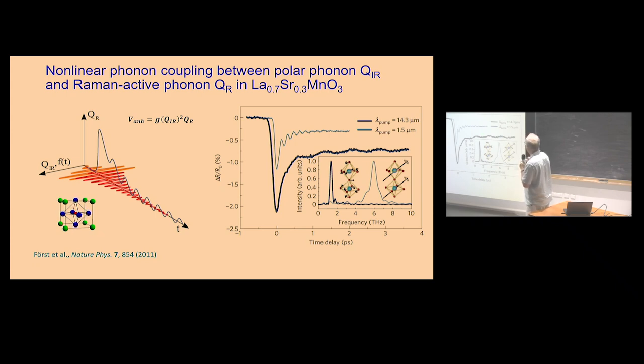They found that even if they pump at 17 terahertz, they obtained a peak around 1.5 terahertz. And when they pump at higher frequency, they obtained a peak at 6 terahertz. So there was activation of phonons due to nonlinear coupling. The infrared active phonons, due to quadratic coupling, and this is, I think, a very important formula, just remember it, take it home. I will use it in many slides.